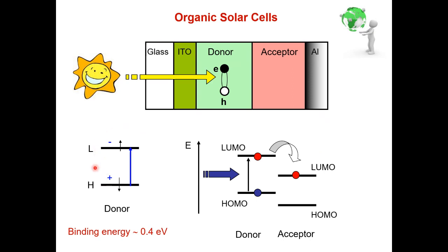Now the thing is, in contrast to all the inorganic material, this exciton is very stable. It's very difficult to have the electron moving to the left and the hole to the right, to break the excitation into charges. This is not spontaneous, basically because the organic materials have a low dielectric constant, and so they are not screening enough the Coulombic attraction between the hole and the electron. And so you have to find a trick to fight against this binding energy, which is huge.